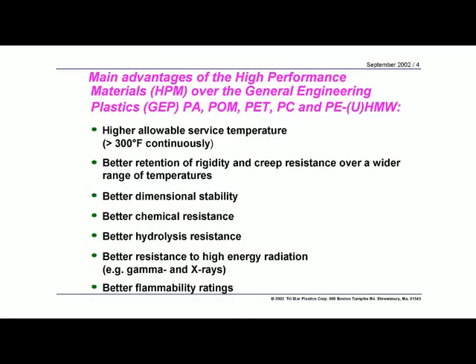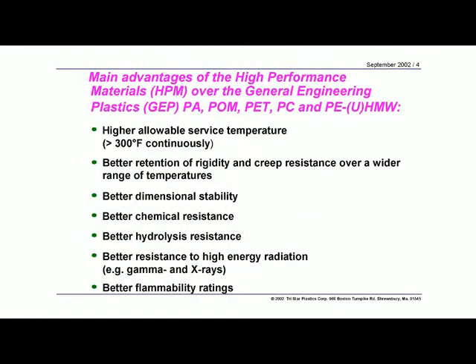Most of these products have pretty good chemical resistance. A few having outstanding chemical resistance, PTFE or Teflon being one of this category. PEEK, also PPS. These materials all have very, very good chemical resistance. The high-performance materials tend to have fairly good hydrolysis resistance, although there are some in the imidized category that you have to be a little more careful with when you're talking about exposure to things like steam or hot water service. These products all have pretty good X-ray and gamma radiation resistance, and then they all have outstanding flammability ratings, most of them 94 V0 ratings, and along with that comes limiting oxygen indexes that are very good. Flame retardancy is pretty good. So these are all inherent to these types of materials as compared to commodity or engineering plastics.